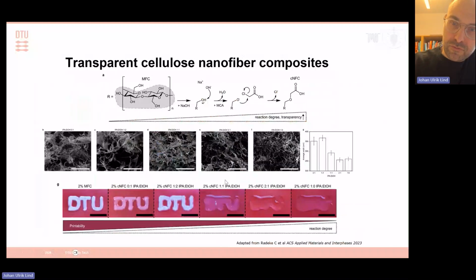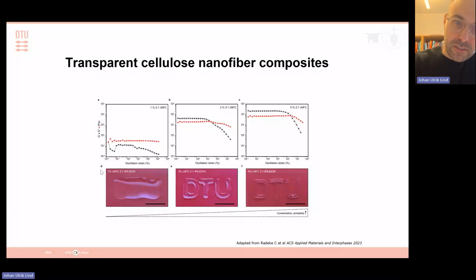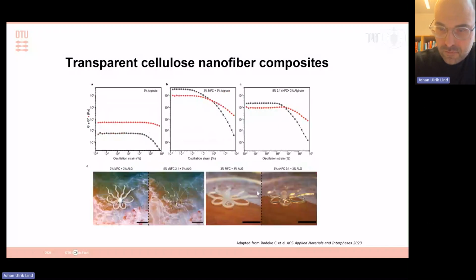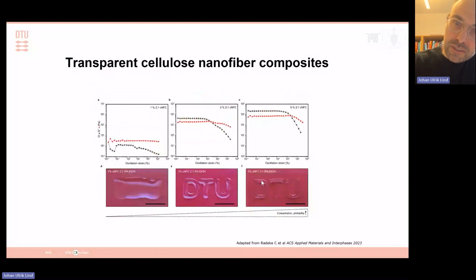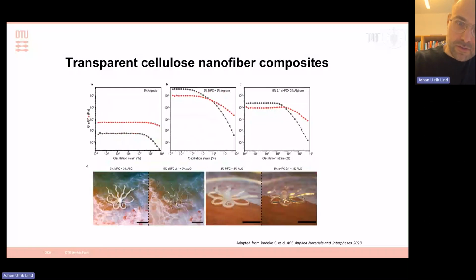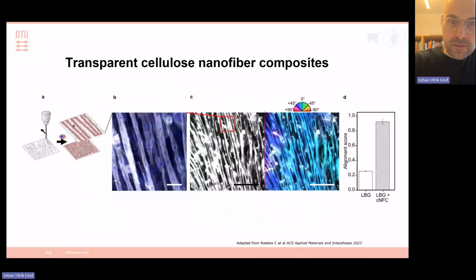Essentially, you need to get some kind of entanglement of the fibers to get nice printable rheology. So by increasing the concentration, we can now get very well-defined prints that are optically transparent, at least transparent enough that we can look at our cells. So that means that the octopus I showed you in the beginning, we can formulate in a more transparent version. But now to the cells.